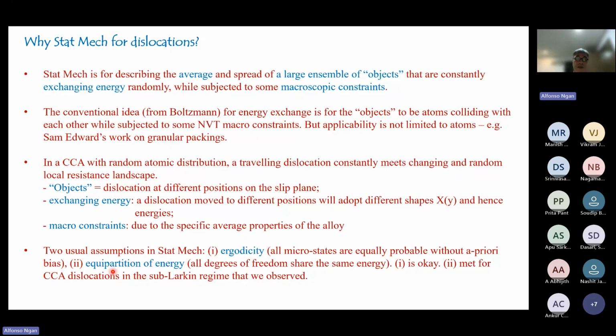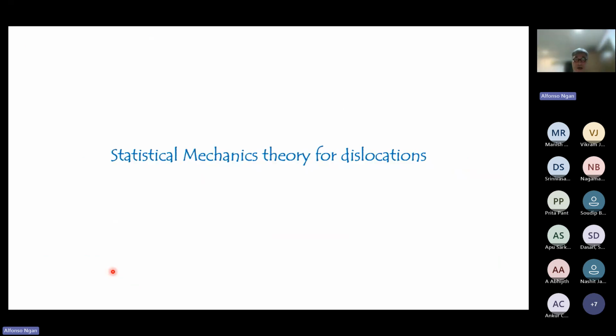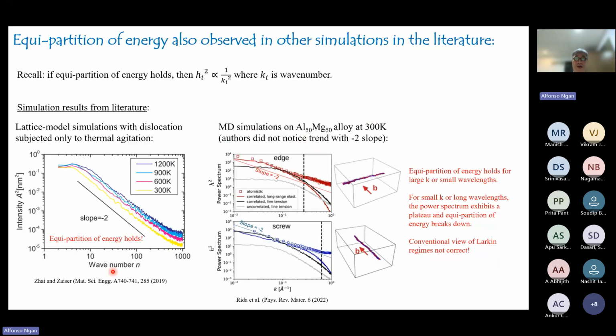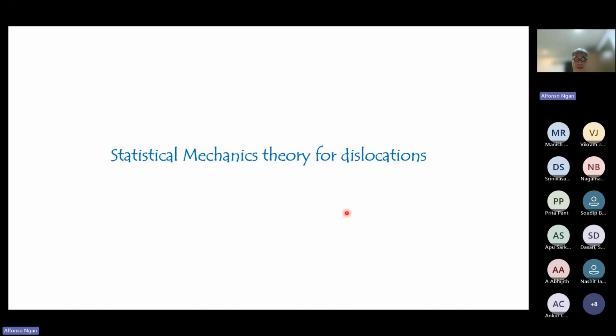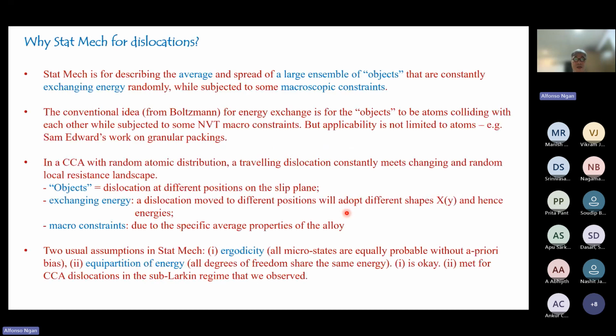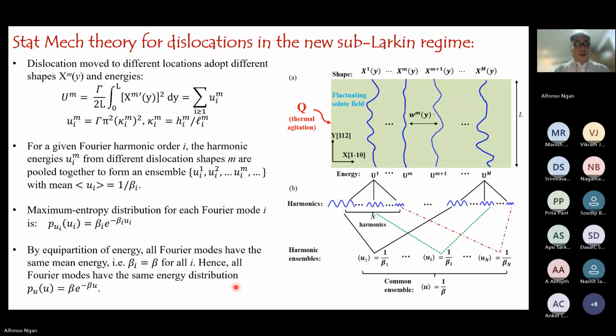The other one is equipartition of energy. We have shown that just now by these analyses; we have shown that this -2 slope is obeyed. So that was also confirmed in the sub-Larkin regime. So with the two conditions satisfied, we can begin to develop our StatMech theory for dislocations. The theory, cutting a long story short, would allow a heat input, so we can be talking about high temperature situations.